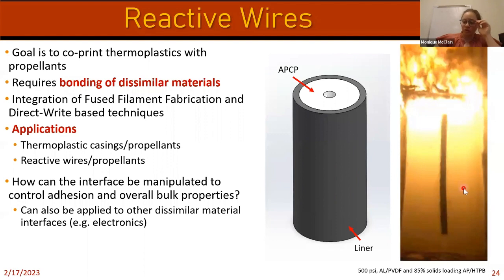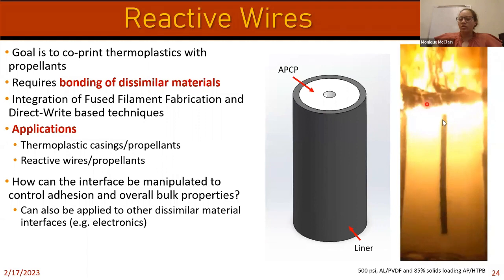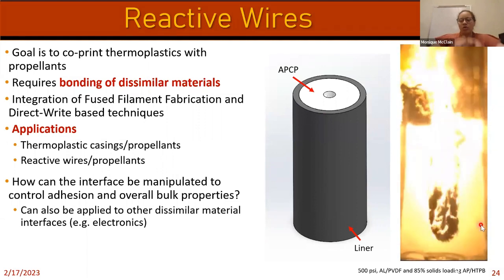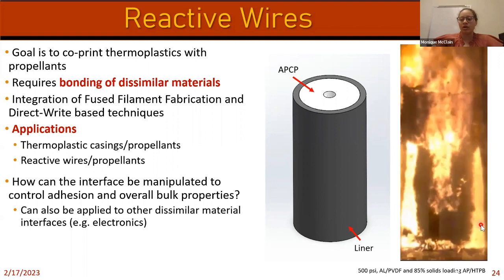I have an example of what that looks like here. Here I have the wire and there's propellant around it. I'm going to play the video. And you'll see once the flame hits this wire, it very quickly opens up that burning surface area. So you can essentially have a fully dense propellant grain where the middle part actually contributes energetically, compared to just air that doesn't contribute any energy. Obviously, if we wanted to make structures like that, we need to be able to understand the bonding between the two, potentially co-print the two, especially if we want more complex structures than just a simple line.